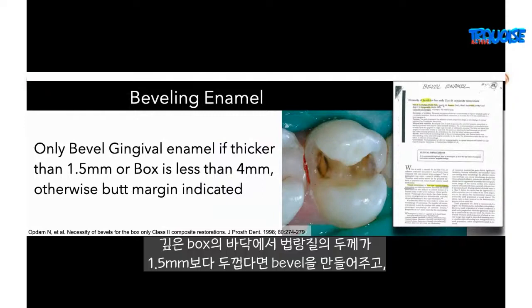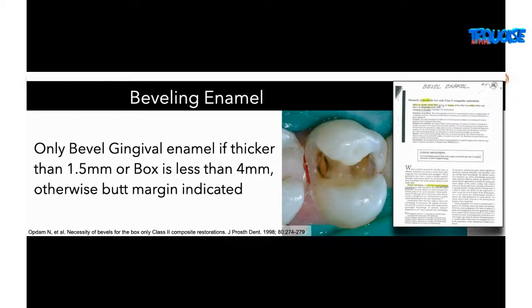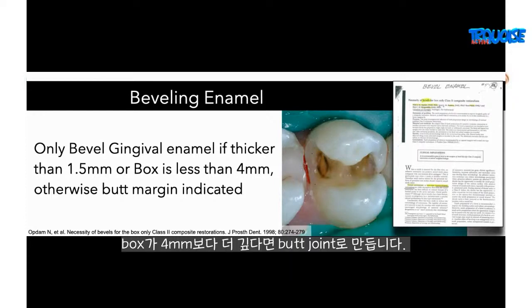In the deep boxes, we bevel the enamel if it's thicker than 1.5 millimeters in the bottom of the box. But if it's deeper than 4 millimeters, then we do a butt joint. We do not try to bevel enamel in that critical 4 millimeters deep into a preparation.